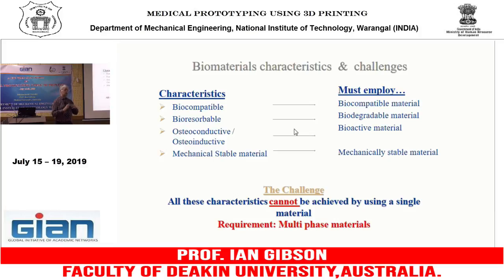What you then do is you might, however, do a coating, and I've seen coatings of hydroxyapatite, for example, which is quite a bioactive material. Okay? But then you might also have some more advanced coatings. Some of the work that I was involved with here was creating homes for coatings which are very highly bioactive, which are protein-based coatings. So in this case, we were looking at, say, what we call BMPs, bone morphogenic proteins.